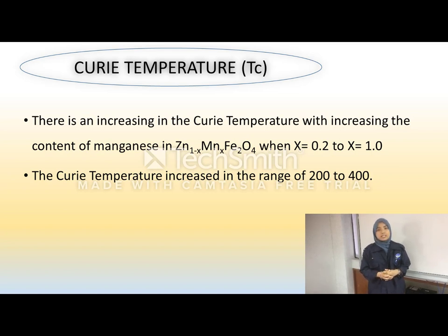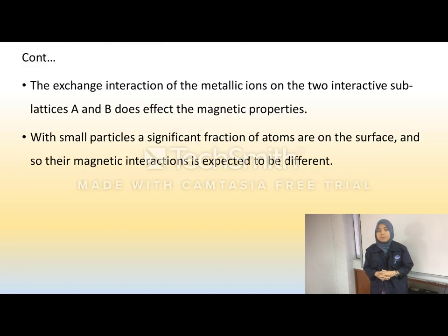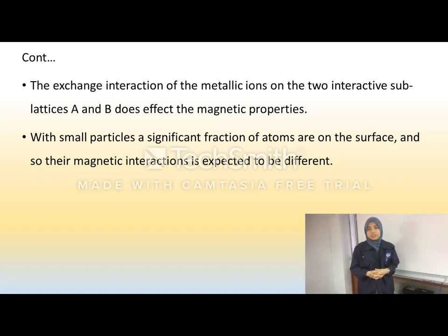As in the study of the bulk counterpart, the Curie temperature values were found to be higher in the bulk ferrite due to deviation of cation distribution in nano-sized particles. Practically, the exchange interaction of the metallic ions on the two interactive sublattices A and B thus affects the magnetic properties. Besides, the surface effect will cause the Curie temperature to decrease too.